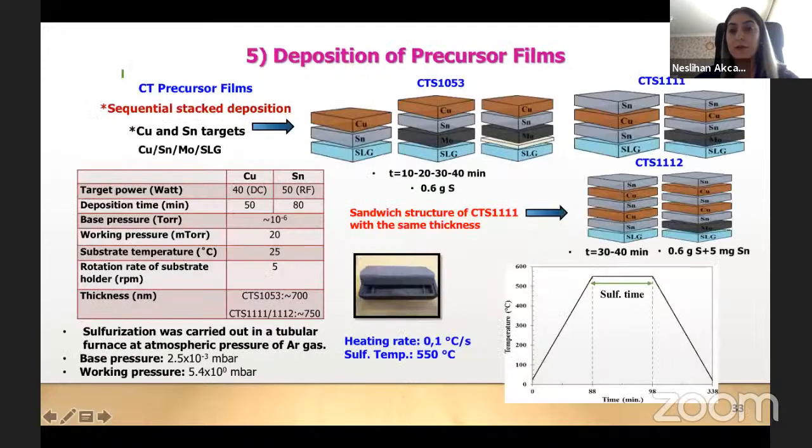For CTS films, we have a lot of experience. We had a lot of experience by these studies, and actually our results on CTS films are better than Kesterite films. Here you see we deposited precursor layers in three different processes at the beginning, and also we still investigate the effect of a thin aluminium oxide layer on soda lime glass substrates. We investigate the sodium diffusion mechanism in these films, and we also produced some precursor films with different structure.